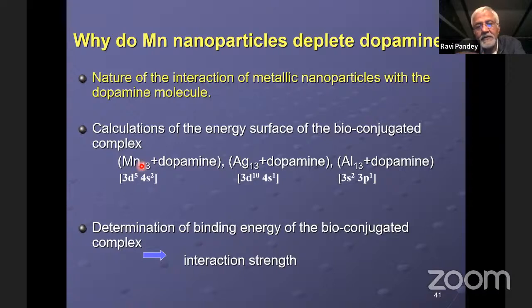And it depends on the degree of symmetry. The more symmetric the system is, the faster the calculation. So we picked, as we know, manganese, a d5 4s2 electron system. And then we looked into silver 13, which is again a d10 4s1 electron system. And as people do in experiments, you have to have what you call the reference case. If we have the d electron system, manganese, the s electron system, silver, why don't we also take the p electron system, which is Al13. So our whole idea is to look at these s, p, and d electron systems and see if we can find any difference in terms of the physics and chemistry at the interface. And from there, we can talk about why manganese depletes the level of dopamine relative to silver or aluminum.